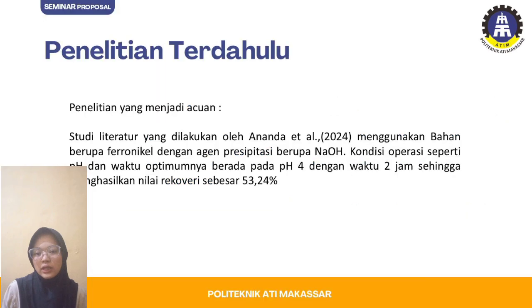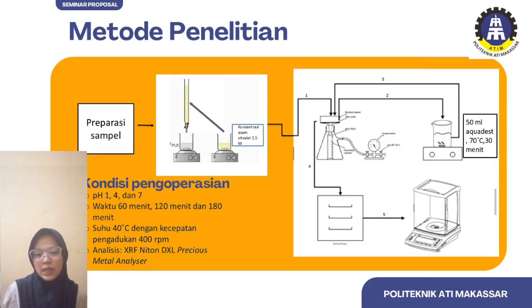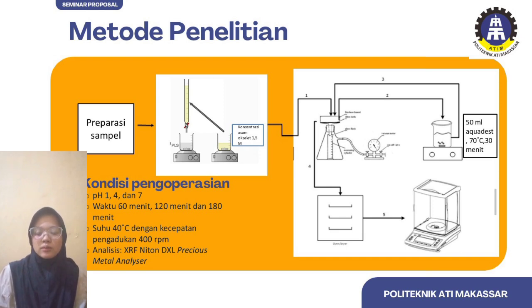As for the theoretical basis, this research refers to a previous study conducted by Ananda et al. 2024, which used ferronickel and NaOH as the precipitating agent. The findings showed that at pH 4 with a duration time of 2 hours, the recovery value reached 53.24. This research was carried out at the material and extractive metallurgy laboratory and the basic process and integrated testing laboratory at Polytechnic Makassar, South Sulawesi, between 14 March until 20 March 2025.